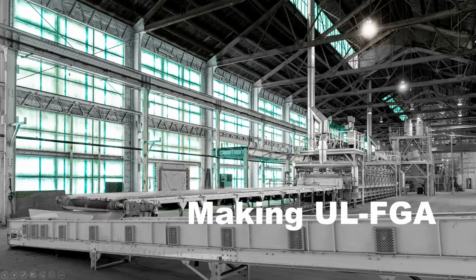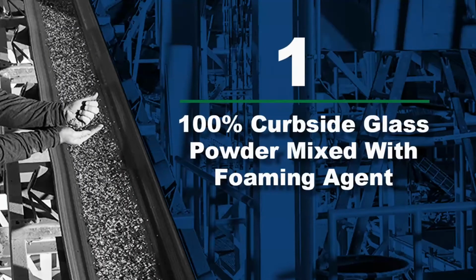Extending from the back side of the kiln is a cooling table, just letting the product have some time to cool after coming out of a very hot kiln. The time that it takes for the powder to move from the front side of the kiln to the back side of the kiln is about 40 minutes. And then it'll take another 40 minutes to move along the cooling belt before it goes to the conveyor and heads outside.